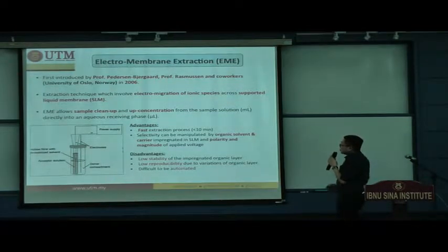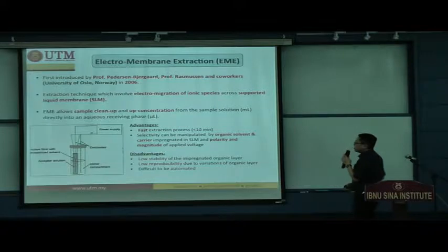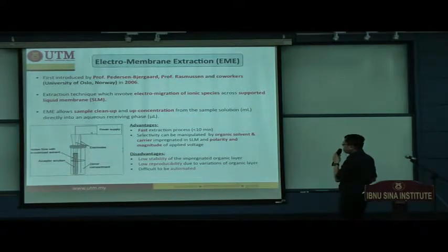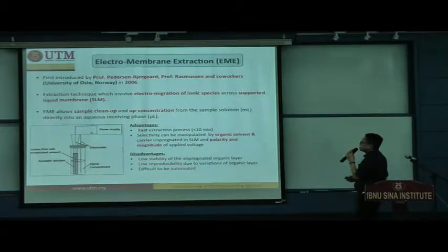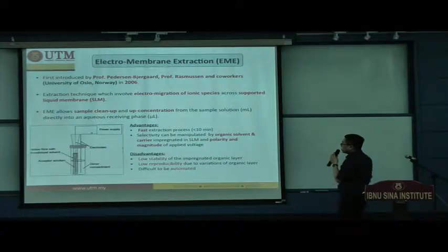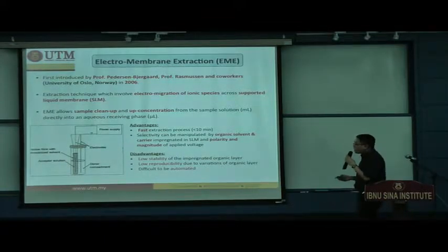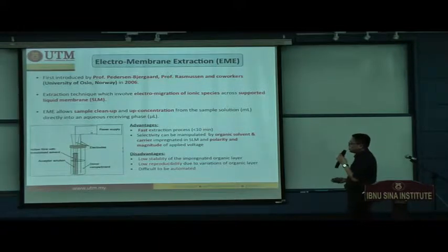The advantages of this technique are very obvious: a fast extraction process, which is normally less than 10 minutes. The selectivity can be manipulated by the organic solvent and carrier impregnated in the supported liquid membrane, and the polarity and magnitude of the applied voltage can also be modified according to the application.